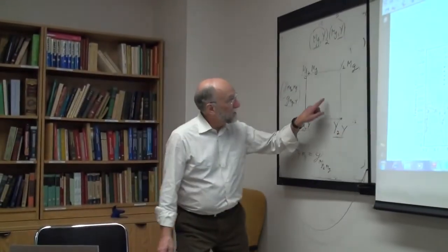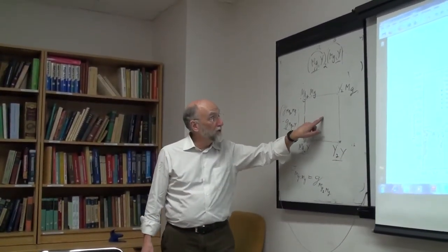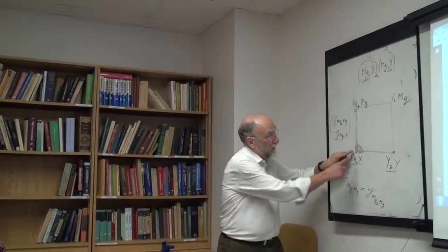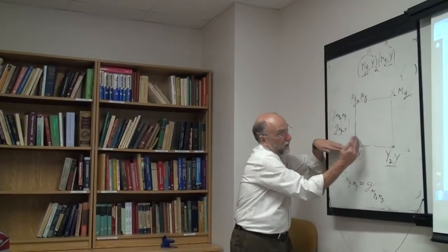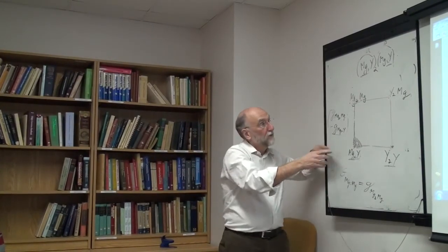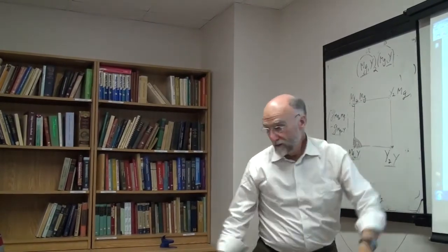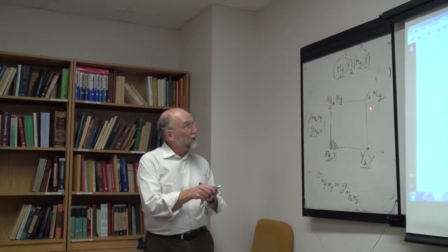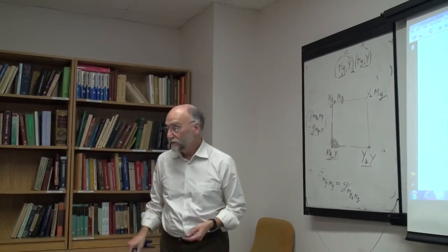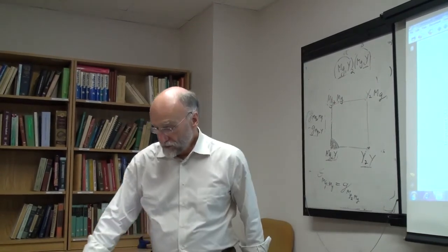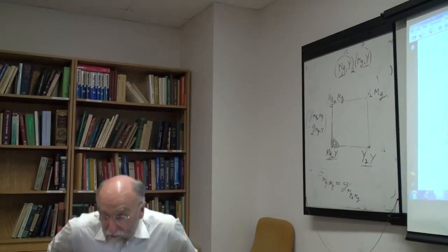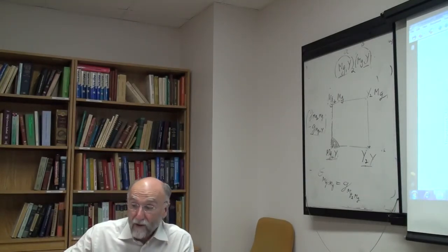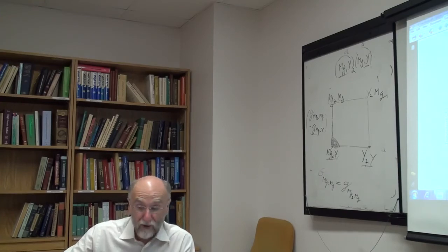Again, the big lambda term, remember, is only important in the middle, and you're far from the middle. The binary terms also are important in the middle of the binary systems. You're way over in this corner here. So there's only really the three G naughts that matter. These three G naughts, this G naught can be basically the same. So that's how you would apply the compound energy formalism to a non-stoichiometric solid with substitutional disorder.